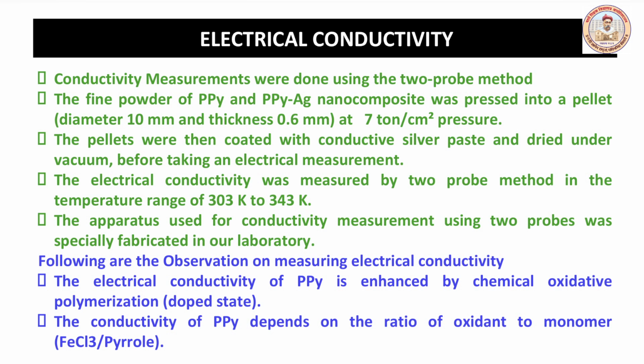The electrical conductivity was measured by two-probe method in temperature range 303 K to 343 K. The apparatus used for conductivity measurement using two probes was specially fabricated in our laboratory. Following are the observations on measuring electrical conductivity. The electrical conductivity of PPY is enhanced by chemical oxidative polymerization. The conductivity of PPY depends on ratio of oxidant to monomer.